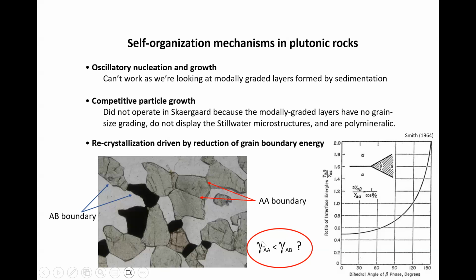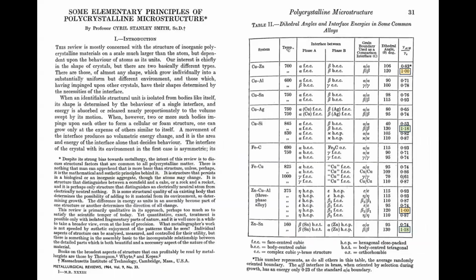Now, if this holds true, if these AA grain boundaries have got a lower energy than AB grain boundaries, then this value here has got to be greater than 1. And in that case, the dihedral angle is going to be greater than 120 degrees. Okay, so all we need to do is measure some dihedral angles in texture equilibrated rocks. Now, this has been done in metals for more than half a century. So the classic paper on this is Smith, 1964.